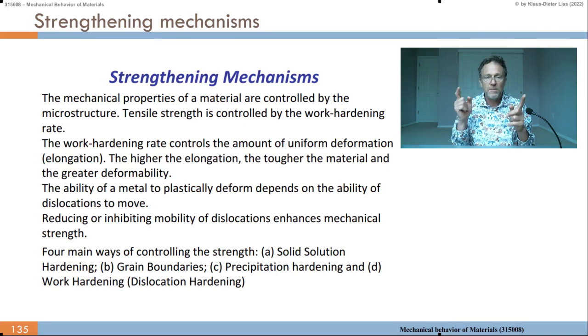So that's the expansion of the stress-strain curve. The ability of a metal to plastically deform depends on the ability of dislocations to move. So for plastic deformation, the major process we introduced here is the motion of dislocations. Reducing or inhibiting the mobility of dislocations enhances mechanical strength. In other words, if dislocations cannot move, we have higher strength of the material and the material becomes harder.